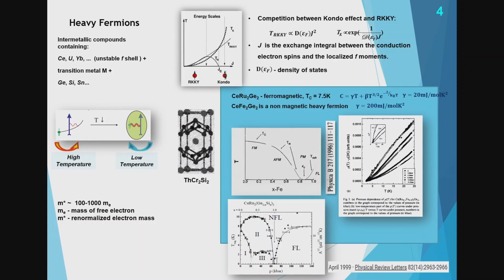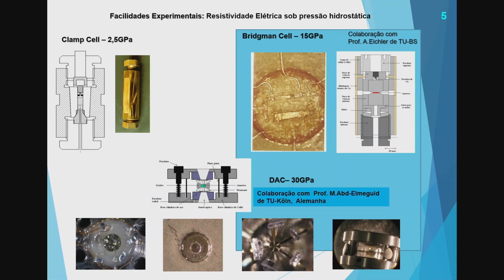Just one example I'm showing to you. This is another phase diagram of ours, which is published somewhere. That is also a kind of chemical pressure in the same kind of material that also goes through a quantum critical point, doping with silicon. Okay, what we use in CBPF in general is pressure. We have 3 kinds of pressure cells. We can use normal clamp cells. Here I put more or less the range of pressure we use. And we can also make experiments with a diamond anvil cell.